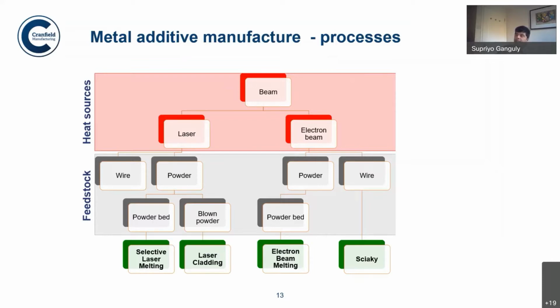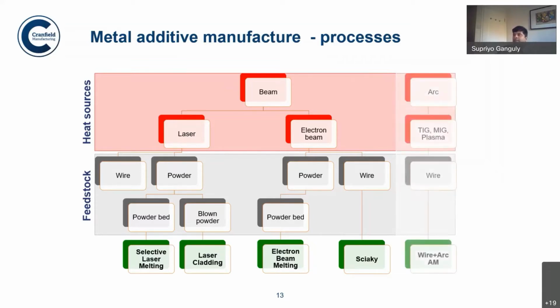Similarly, electron beam welding also can be done with powder or wire and powder bed, and electron beam plus wire can produce very fast, or the productivity is quite high, which is known as the Sciaky process. We process in this area, which is using arc as a power source, and this can be either traditional GTAW welding or a MIG welding or a plasma welding.